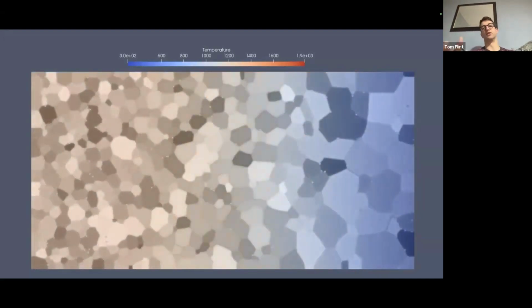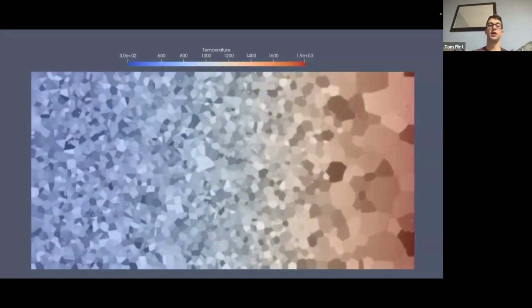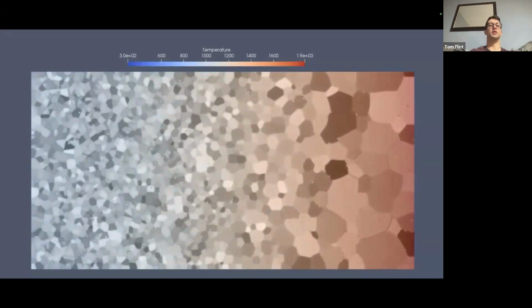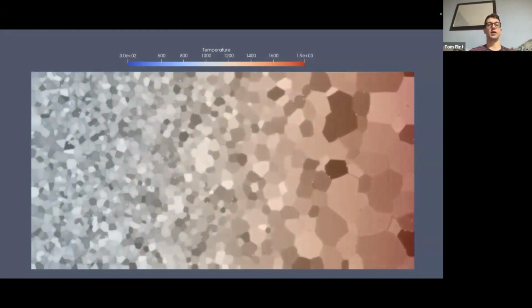animations. This is looking at the coarsening in a heat affected zone of a titanium 6-4 alloy. The color is the temperature, and then you can see the microstructure. We had some pinning particles in this microstructure, and what we were investigating here was the effect of the thermal properties of those particles on the evolution of the microstructure.